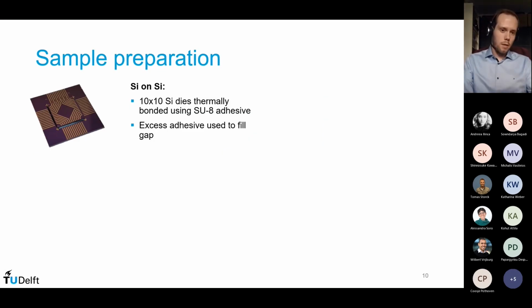So how do we now make this connection on the side of a chip? To do this, we fabricated dummy samples of silicon on silicon to prove that this process can work. This is the simplest possible device that we can make. It's just gold lines placed on silicon. So we've glued a 10 by 10 millimeter silicon die on a larger one to create this step, and we use the excess of adhesive to fill the gap between the two substrates. This way we have a continuous transition from the top to the bottom.